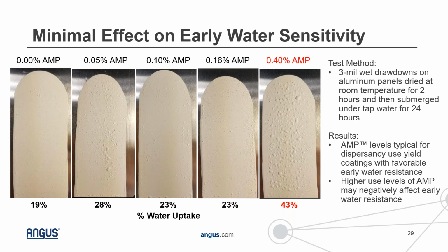I did just want to point out that if your AMP concentration is too high, you can find negative effects, right? So on the far right is an example showing where we use 0.4% AMP on total formulation weight. And for this particular formulation, that was a bit too much and started to show some detrimental effects to early water sensitivity. But if we stuck within the levels of AMP that we used here to be used as a co-dispersion in the grind, we really didn't see too many negative effects, which is great.